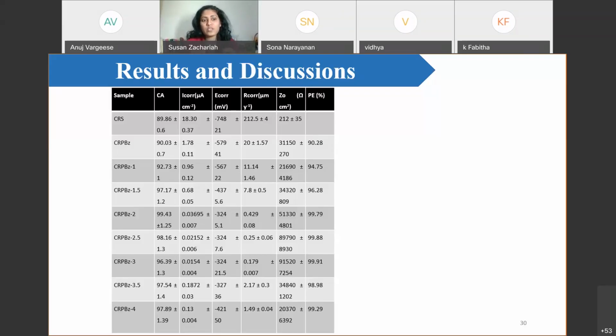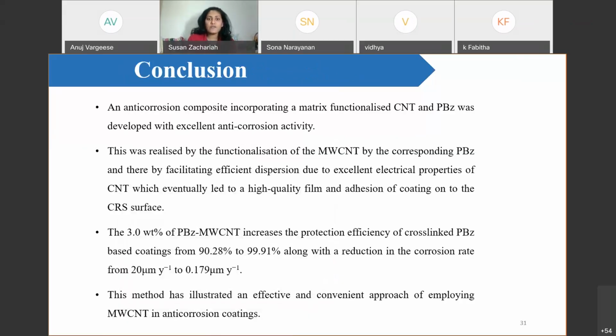Here we have used different weight percentages of PBz-functionalized CNT, from 1 to 4 weight percent, and we found that when we used 3 weight percent of PBz-CNT, it gave the better protection efficiency of 99.91%. So we made this the optimum percentage of functionalized CNT to add to the PBz solution to make the coating. The conclusion of this work was that an anti-corrosion composite incorporating a matrix, functionalized CNT, and PBz was developed with excellent anti-corrosion activity. We also got the optimum weight percentage as 3, with a protection efficiency of 99.91.